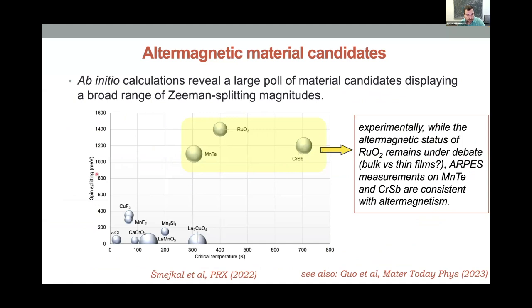So this is a plot from their paper showing the size of the spin splitting and the critical temperatures. And you see that these three, chromium antimonide, manganese telluride, and ruthenium oxide, have the highest spin splittings, with phase transitions above room temperature. And of course, because of these reasons, they have also been studied more extensively experimentally. Manganese telluride and chromium antimonide, recent ARPES, including spin-ARPES measurements, I think show very clear evidence for the altermagnetic character, whereas with ruthenium oxide, there's still debate going on, and I'm not going to talk too much about it.